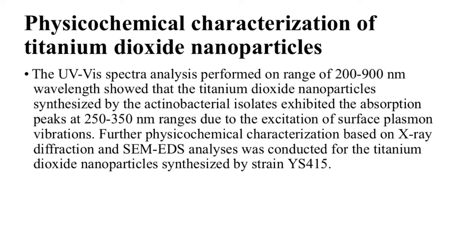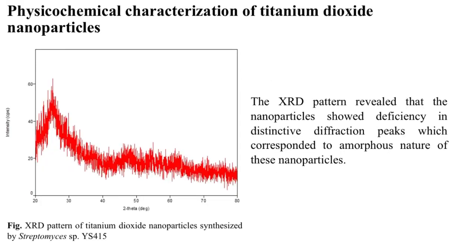Further physicochemical characterization based on X-ray diffraction and SEM-EDS analysis was conducted for the titanium dioxide nanoparticles synthesized by strain YS415. The XRD pattern revealed that the nanoparticles showed a deficiency in distinctive diffraction peaks, which corresponded to the amorphous nature of these nanoparticles.